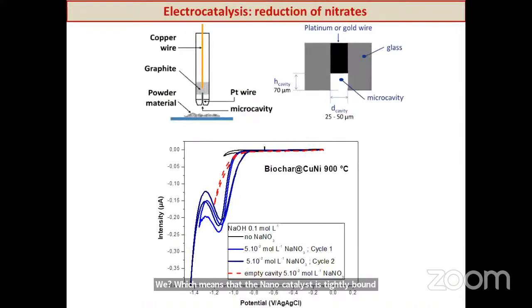We have gone also with some collaborators to electrocatalyzed reaction. This is their work with microelectrodes, and we have microcavity electrodes. We have prepared copper nickel on biochar powders for the catalyzed electroreduction of nitrates into NH3 or N2 by electrochemistry. In this work, however, we had to go up to 900 degrees to have a very graphitized material, because biochar prepared at 400 or 500 degrees is not yet sufficiently conductive to be used in electrochemistry and permit the electron transfer. So this work is under progress and will be submitted to an electrochemistry journal.